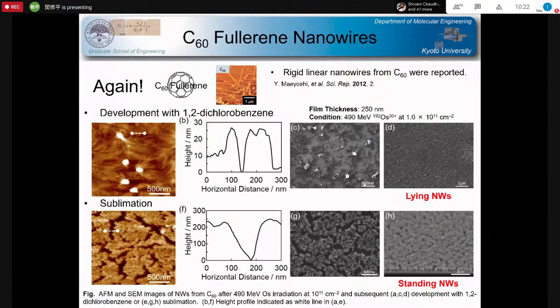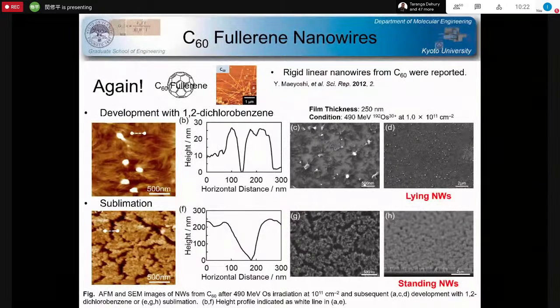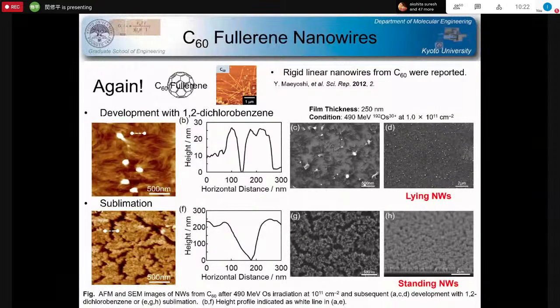And again, back to the Buckminsterfullerene systems. As you saw in the previous slide, Buckminsterfullerene gave very straightforward nanowires. In almost all cases, we employ the protocol of removing the unreacted part of the organic materials by solvent treatment. Initially the molecules are dissolved in the organic solvent, and after the irradiation, the unreacted part of the organic substances is removed by the dissolution process with the organic solvent.